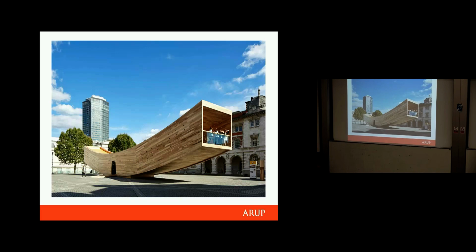thermally, wood is really stable. The actual issue is that across the grain, wood will shrink and swell quite a lot. During construction, most CLT or glulam is manufactured at about 12% moisture content. It will generally go up to about 15 or 16% moisture content during construction, and consistent with that, your glulam beam will swell by about 1% across the grain. So if you've got a 1 metre deep glulam beam, it won't get any longer, but it will get about 10 millimetres deeper. Then after you switch on the heating in the finished building, it's going to dry down by about 4% moisture content, or about 1% overall. So it's the cross-grain drying shrinkage that you need to deal with.